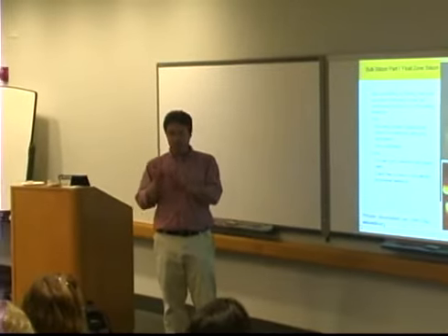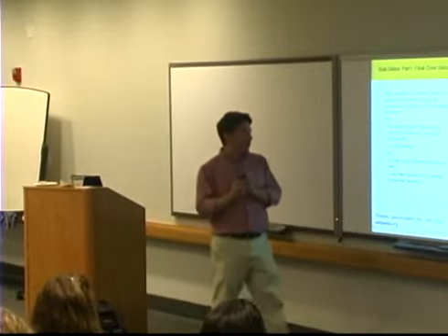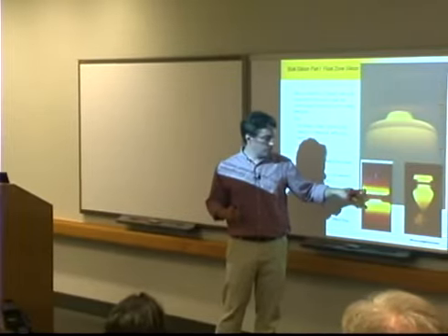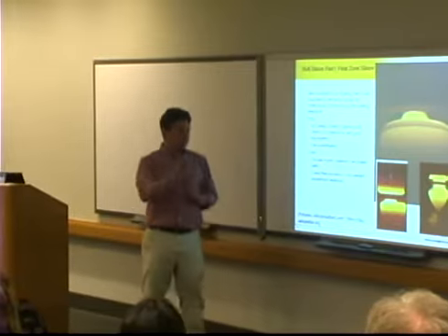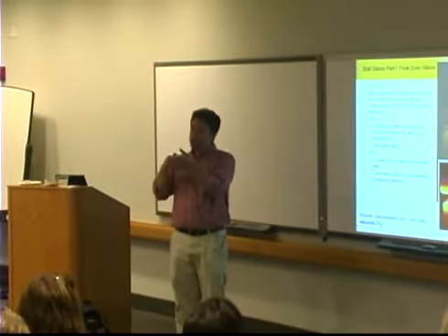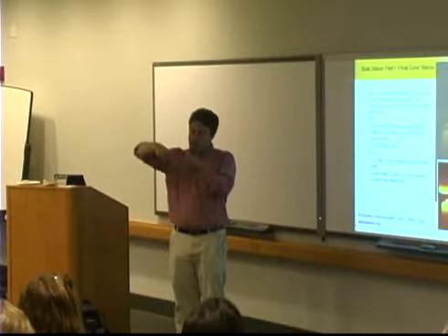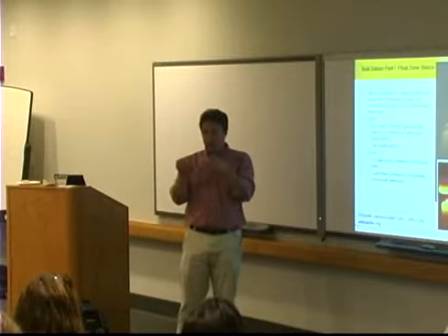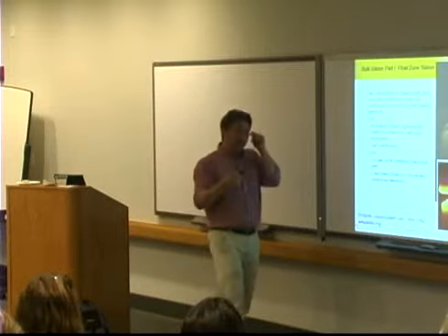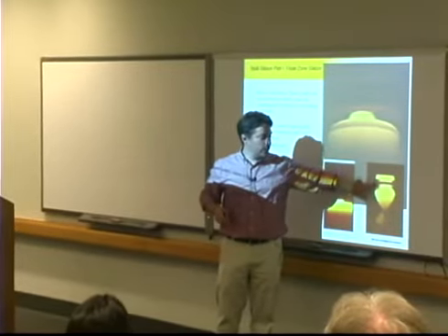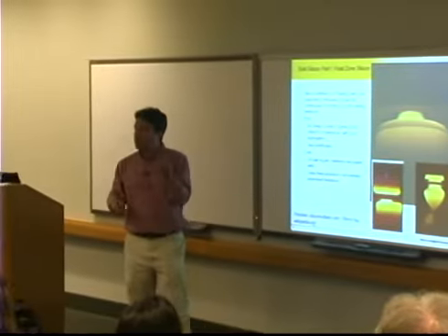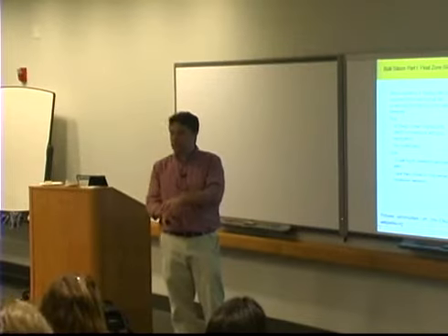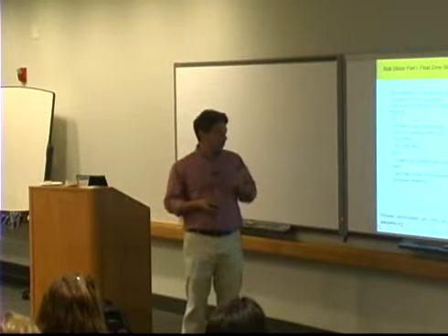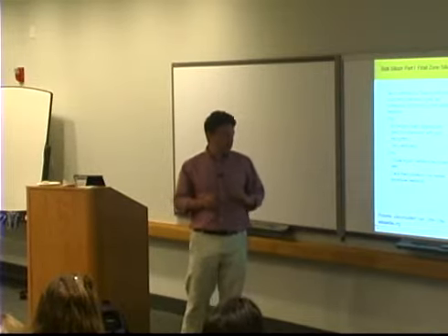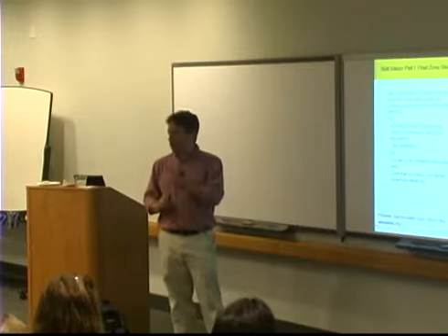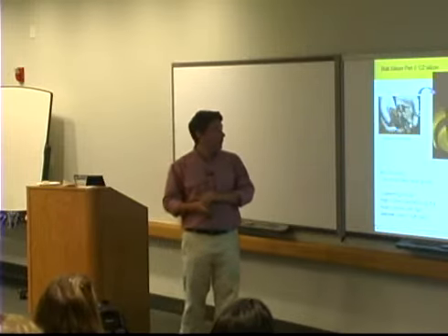Normal polysilicon feedstock has these kind of cracks and a kind of cauliflower shape to it. And the problem with that is that this induction here creates an electrical current that travels around the outside of the silicon. And if there's a crack, then the induction is not going to jump the gap there. Essentially, it's going to shrink in and go inside of that crack. And so the melting is not going to get out to the edges. You're going to get this kind of hollowing out of the middle. And in the extreme case, they talk about basically these long unmelted icicles ending up left behind. And as you're pushing it down, eventually that's going to contact the heater, and that's going to form an arc, and you're going to have a lot of trouble with your process. So they like crack-free polysilicon rods, and those are generally at least twice as expensive as the standard silicon feedstock. Whoops. Okay, CZ silicon.